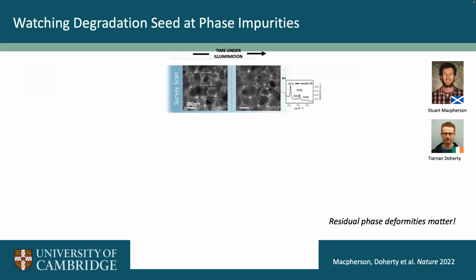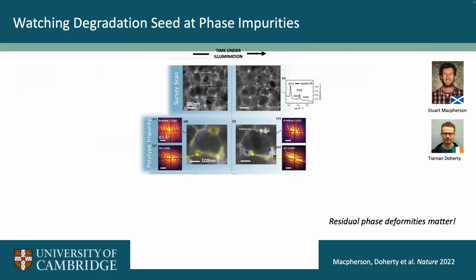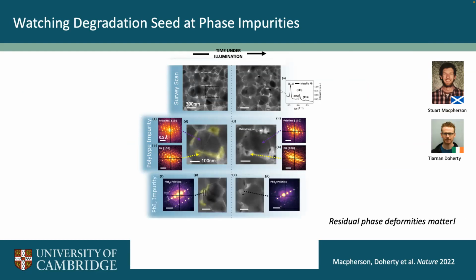I just want to show one example where these phases are really problematic, and this is looking at before and after long-term illumination. So we're illuminating the sample over time and looking at the same scan area. And what we see is where you see these defective regions, shaded in yellow, afterwards we've got material loss there, and we're starting to see degradation of these specific sites associated with these shaded regions. And we can see that also in another example here. We can see where these yellow regions are. Afterwards, we're seeing material loss at these sites.